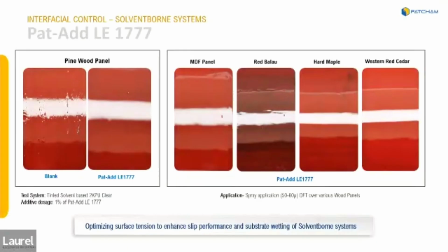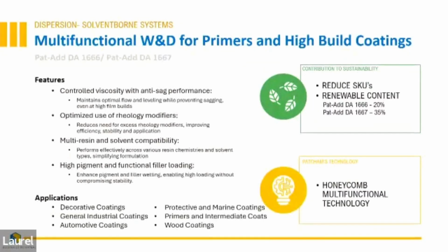Wood is a very interesting substrate for formulators because it's a natural substrate, has different degrees of porosity, different types of waxes and oils at the surface. And so it's a balanced combination of wetting, spreading, and penetration, all simultaneously happening, to control the contact between the coating and the substrate, and then the coating and the upper surface, the hydrophobic surface of that coating, to give you then these various appearances.